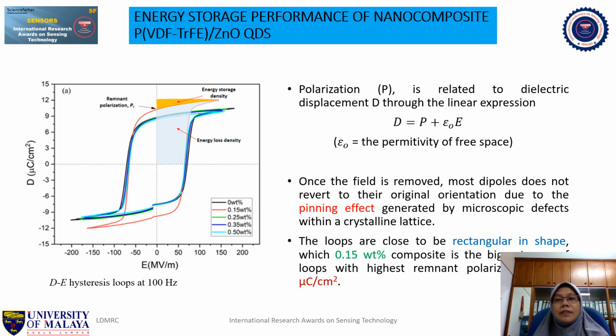The energy storage performance of this nanocomposite was investigated by using the hysteresis loop of ferroelectric properties. This figure here shows the hysteresis loop of several nanocomposites with 0 weight percent of zinc oxide to 0.5 weight percent of zinc oxide inside the polymer host. We know that polarization can be related to dielectric displacement through this equation as shown here, D equals P plus epsilon naught E. So in the ferroelectric test, we increase the electric field until we reach saturation and then revert the direction of the electric field until we achieve the negative saturation state.